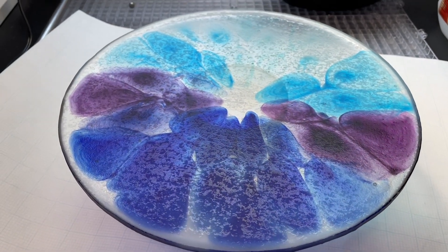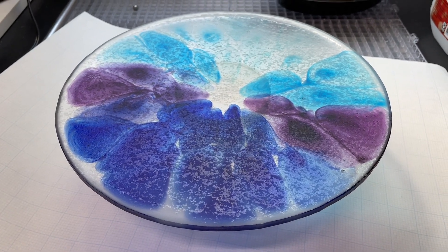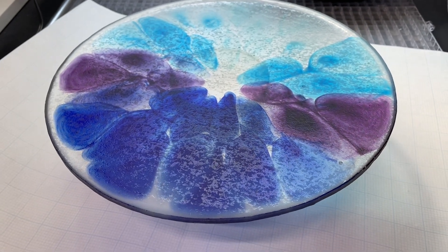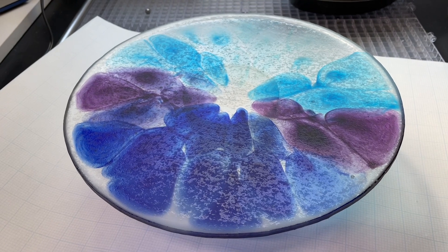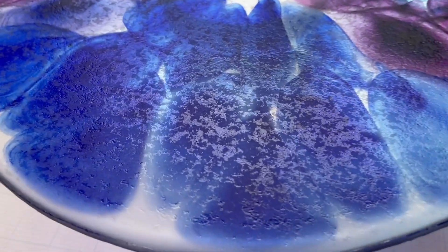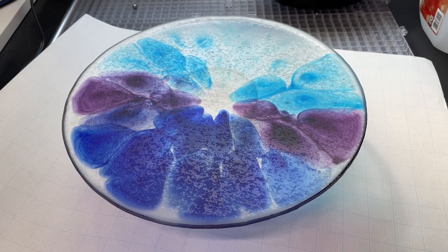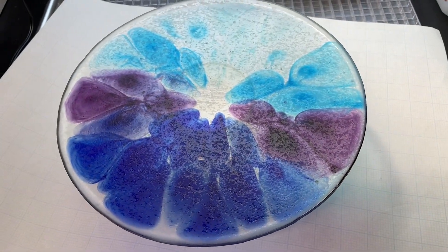All that footage was shot more than a year ago — early February 2021 during the Texas deep freeze and winter storm. When the piece came out I wasn't sure what to do with it, so I set it aside. I finally dug it back out. There was just a little cold working needed — I used my grinder to clean up the edge where there were some inconsistencies. The top needed smoothing where the stringer was. I decided to flip it and refire. I took a diamond pad to the bottom to rough it up and clean up imperfections, then dusted it with powder and I'm doing a full fuse to let it spread out a bit and get a nice shiny finish before slumping it into a bowl mold.